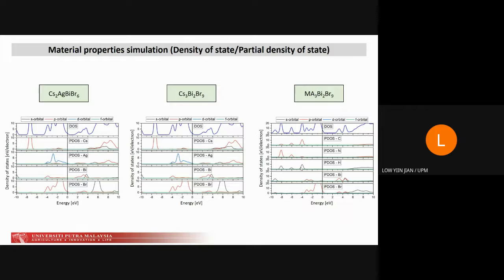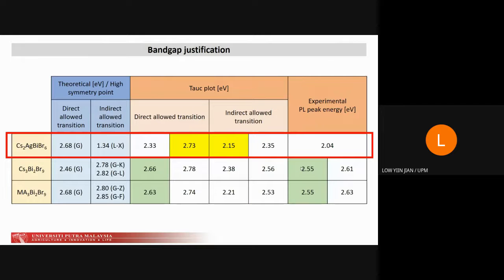While the A-site ion is not contributing much in the band structure engineering, as it is only an inclusion in the perovskite structure without having any physical bonding to the octahedron. And all of the bismuth-based perovskites show the low band gap value. Hence, from the simulated band structures and determined optical band gap, the direct transition is near to each other, but the indirect transition deviates significantly.